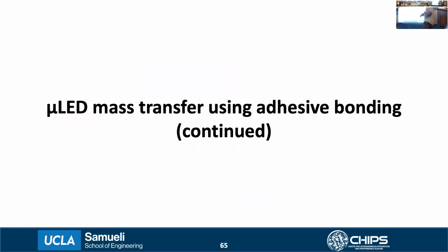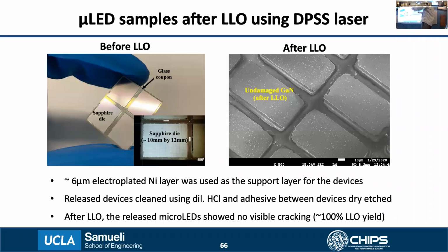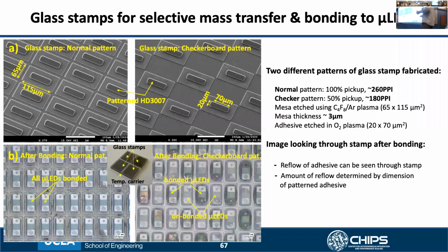Now let me continue with the micro LED mass transfer using adhesive bonding. I'll quickly move through this, as these are just experimental results. Once the samples were bonded, we performed the LLO process. Now you see the micro LEDs sitting face down on the temporary glass carrier with almost 100% LLO yield.